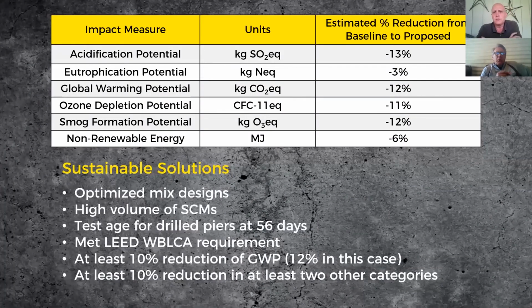The improved mixes were analyzed by the software to determine the embodied environmental impacts per cubic yard. And based on that analysis, the concrete mixes were implemented into the whole building LCA. They also varied the age for testing concrete to allow for higher volumes of fly ash. For example, since the foundations did not see the full loads until much later in the construction process, they did specify testing concrete at 56 days for the drilled piers.